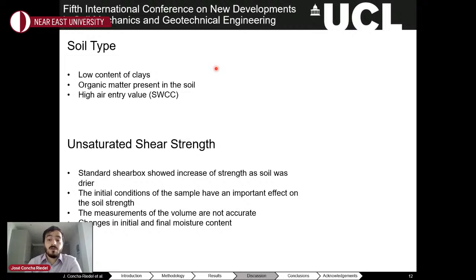With regards to the shear box test, it was discovered that the soil has higher strength as it goes to a drier state. However, achieving the initial conditions of the sample is quite difficult and can tamper the results, for example, the points that were plotted in gray. This apparatus also does not provide accurate measurements of the volume changes, and because it is open, the moisture content of the sample can change, which makes it impossible to know the moisture content of the sample during the test.